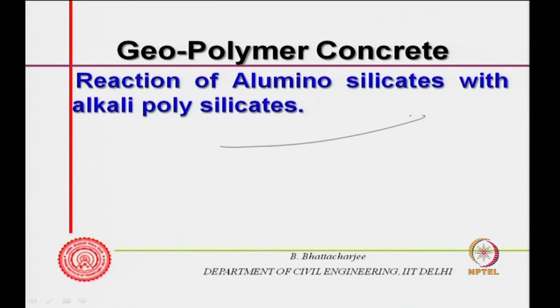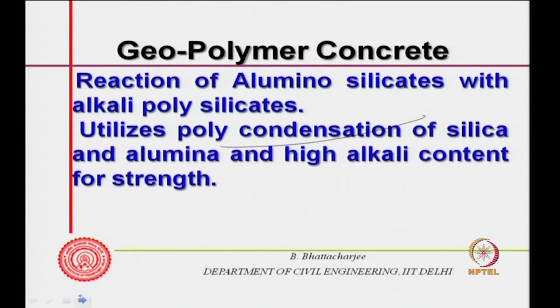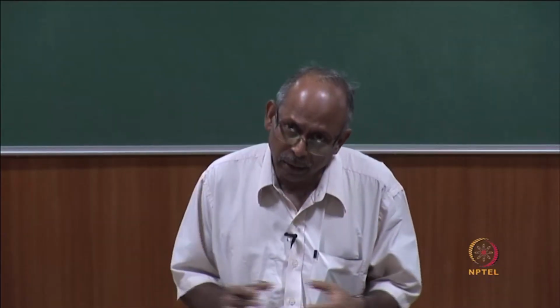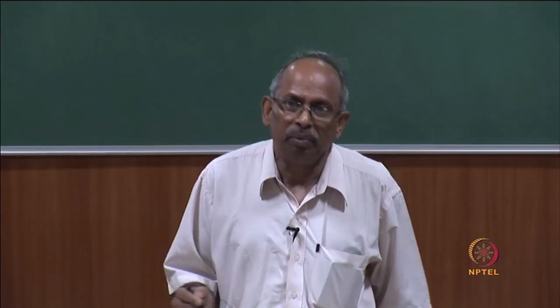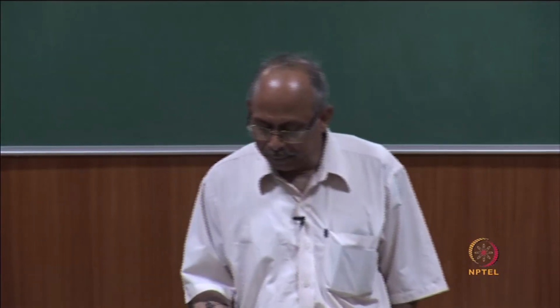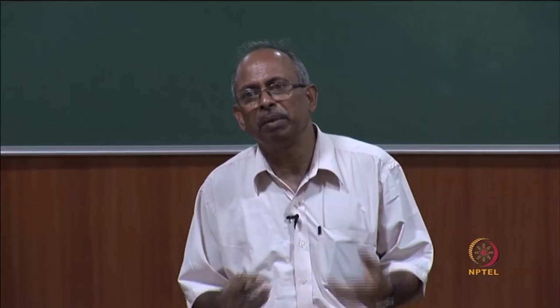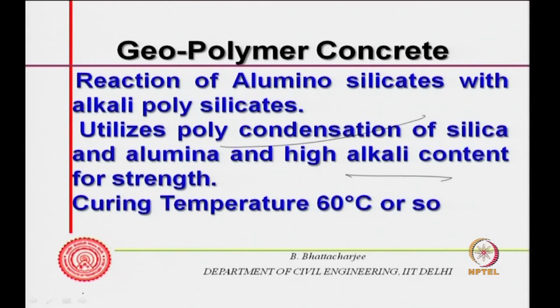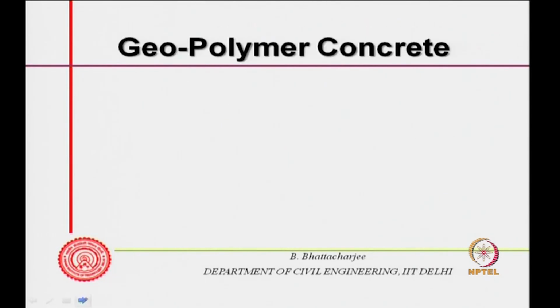So, this is a reaction of aluminosilicates with alkali polysilicates, utilizing polycondensation of silica and alumina and high alkali content for strength. Basically, a condensation reaction is a polymerization reaction where some of the products are lost as a byproduct, to make a polymer. So, polycondensation reaction is that. Because of the polymer solidifying, it gives you strength. Initially plastic, then it polymerizes, becomes solid, and gives you the strength. One problem has been that the curing temperature is 60 degrees centigrade or so, but remember it does not use any cement altogether.